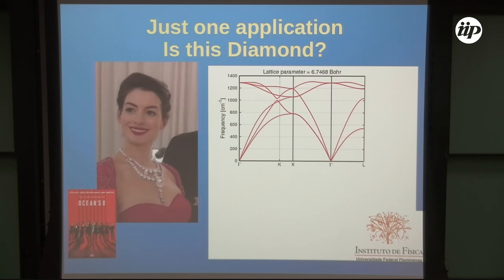This is the phonon dispersion of diamond. The first important thing is that usually we use visible light, or maybe infrared or ultraviolet, but the wavelength of light is very large compared to the lattice parameter of a solid. So usually the wave vector of the light is very small compared to the phonon wave vector. So in order to have momentum conservation, if you have a single process of Raman scattering, you will measure only phonons at gamma. So that's number one. What is a single process? It's a process where you create, for instance, just one phonon. So you need to go close to gamma because of conservation of momentum and because usually you use light with very small wave vector.